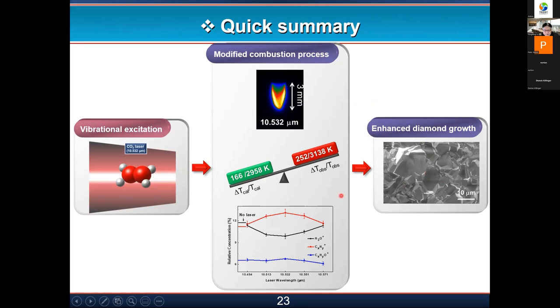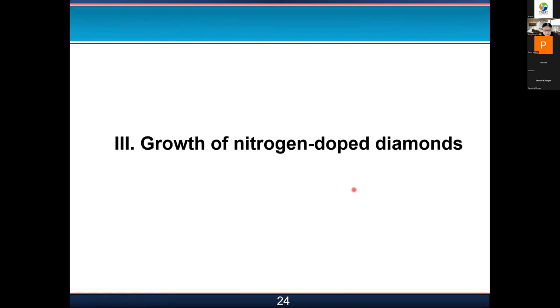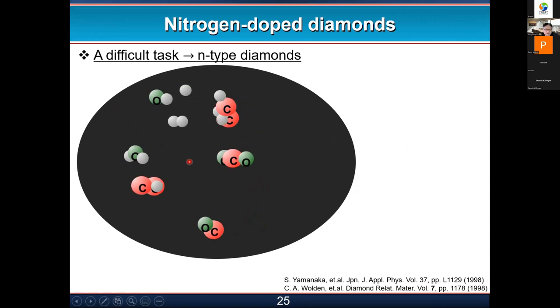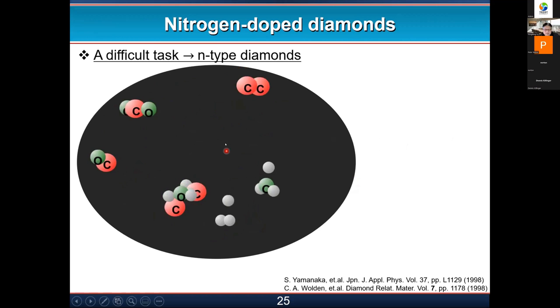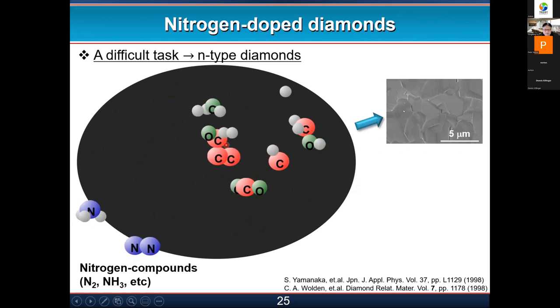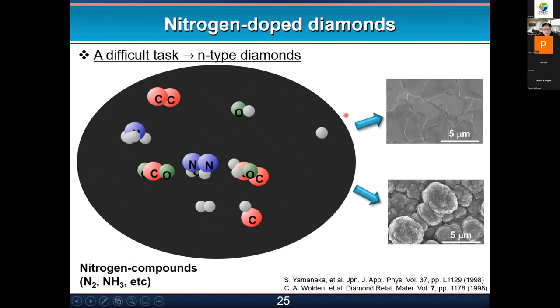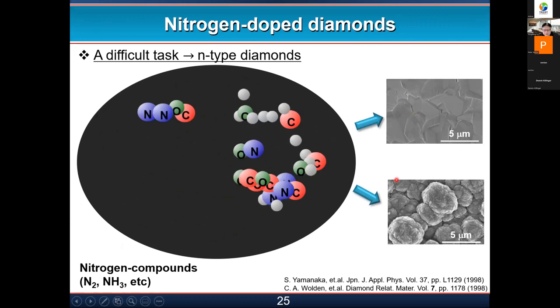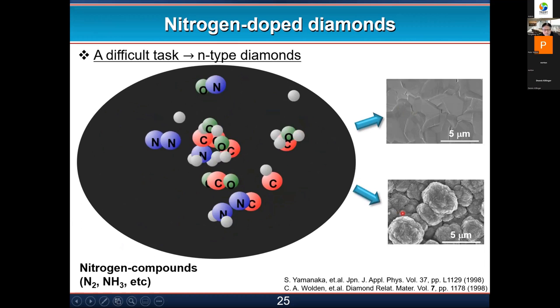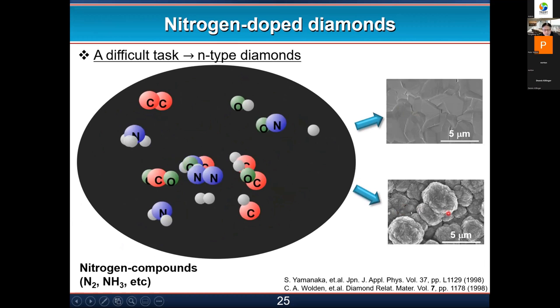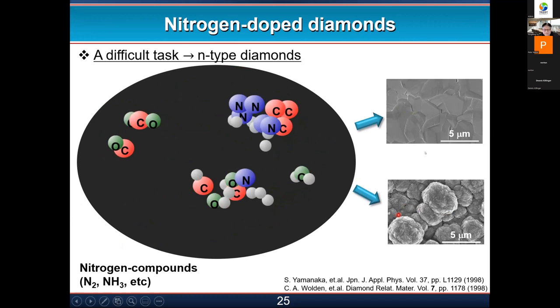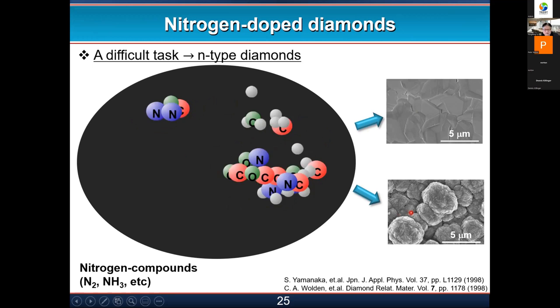And then we use this method to dope nitrogen into diamond. Once you have doping, usually crystallinity will disappear. Here we use ammonia as a source of nitrogen. If you don't put ammonia, you usually get good crystals. But if you add a little bit of ammonia, the crystallinity will disappear. What you get is probably nanocrystal diamond or amorphous diamond, and you cannot get a high quality diamond crystallinity when you have nitrogen doping.